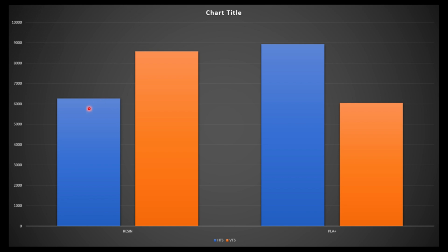I don't know why this is. This shouldn't be the case. In theory, resin, I forget the right terminology, but resin prints should be the same strength no matter what the orientation. They're kind of like an injection molded part that way. It just makes a solid piece of material, and it should be equal in horizontal and vertical. In this case, it was not close to being equal. The horizontal part was much weaker. Why was this? Probably because the part wasn't as cured as much, or it was printed differently than the horizontal part. I'll email the gentleman who sent me this and try to determine if that is the case and try to work that out. But more testing is really needed to know for sure what's going on there.